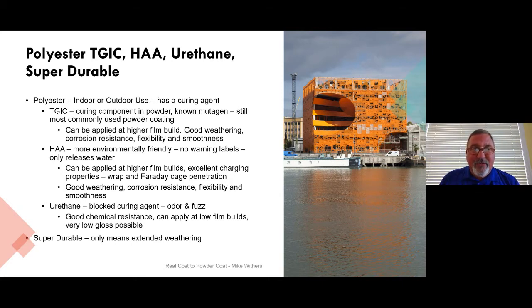For the HAA curing component, you'll hear that referred to as a non-TGIC or TGIC free, or just simply as a polyester HAA. They're more environmentally friendly. The curing agent only releases water, and they can also be applied at higher film builds. Initially, you could not do that, but there have been recent advances in the last couple of years where you can apply at a higher film build. They have excellent charging properties, and so if you're typically using a TGIC polyester and you make a conversion to an HAA, then you're going to typically have to turn down gun settings because they have such excellent charging properties. So that means wrap around the part and then Faraday cage penetration.